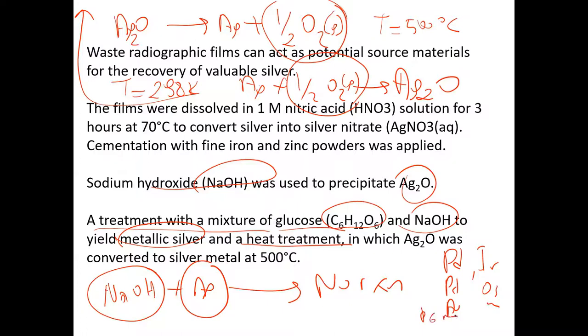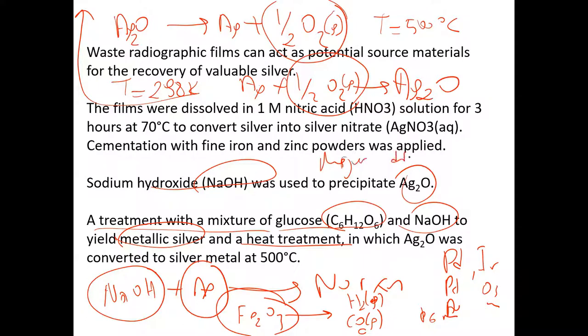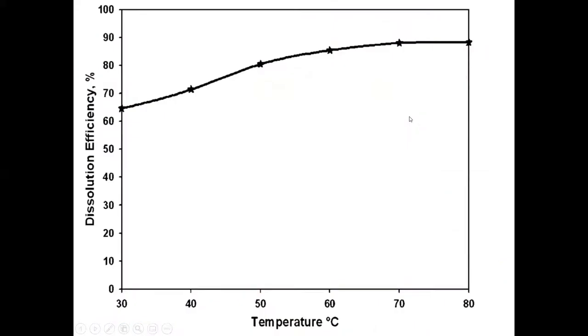This heat treatment method is successful for precious metals like palladium, platinum, gold, iridium, osmium — the PGM metals. But this is not valid for iron oxide. You can never isolate iron from iron oxide with heat treatment alone. This is the reason for reduction using hydrogen gas, carbon monoxide, or elemental carbon. This is a major difference between noble metals and base metals.